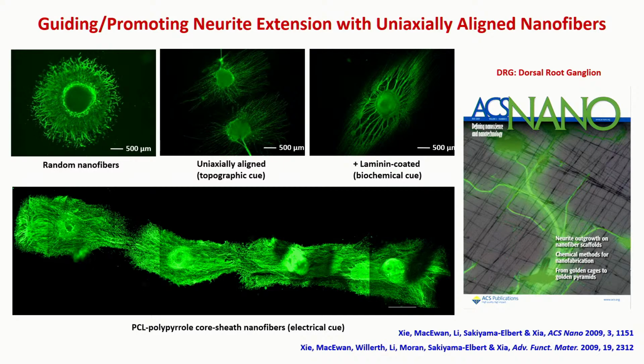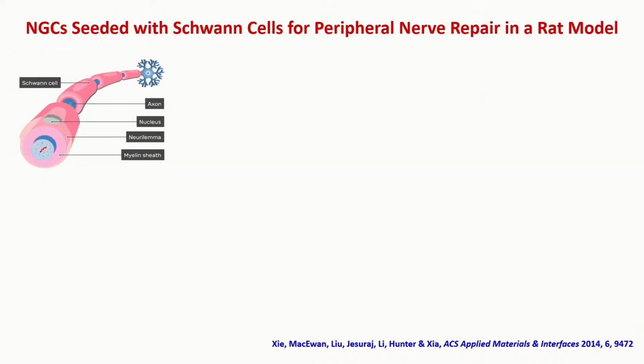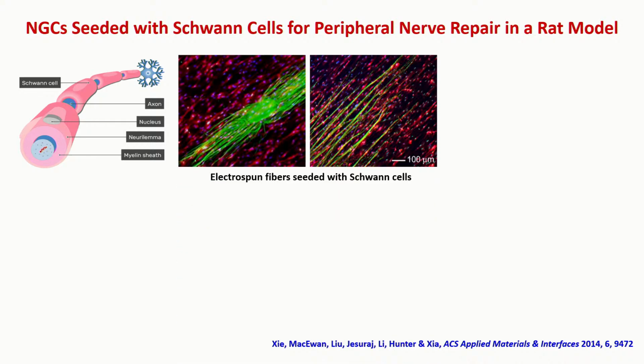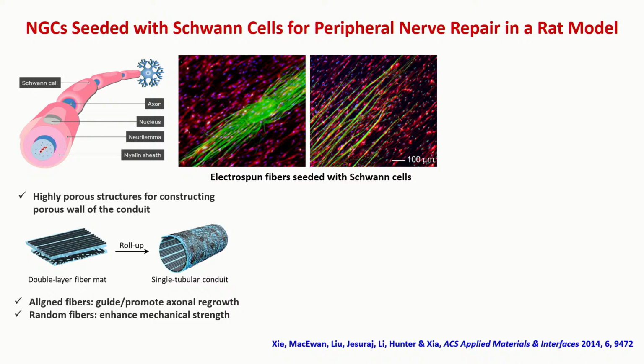But that's not the current interest in my group. Right now, we just focus on peripheral nerve repair. And as I mentioned earlier, one of the major requirements for peripheral nerve repair is really the Schwann cells that eventually will form these myelin sheaths over the nerves, and that is very important to provide them with the right functions. And so that's why in one of the early studies, we tried to seed the electrospun fibers with Schwann cells, and then we cultured DRG on top of it. So as you can see over here, these Schwann cells and these neurites do interact very favorably. Actually, they can form a layer around it. And so that's why we moved one step forward, trying to apply this to in vivo studies.